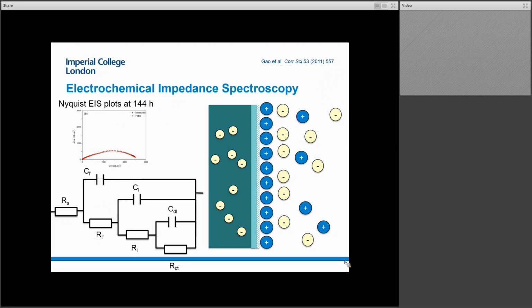So again, we'll find that we would have a resistance to our solution, and we'd have a resistance on that new layer, and a capacitance, I should say, and then the same again on the original layer. Now, the resistance and the capacitance doesn't have to be the same as it was at the earlier timestamp. It can evolve. And in some ways, that's one of the things we're looking for, is how that layer may evolve. And then again, we're going to have resistance to charge transfer and capacitance of our double layer. And you can see that the data's in the plot that they provided. It looks like it fits quite nicely.